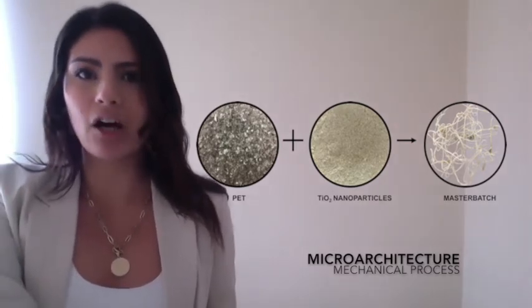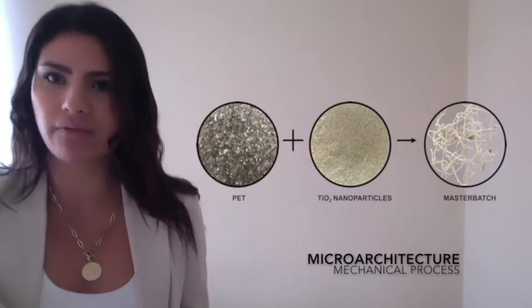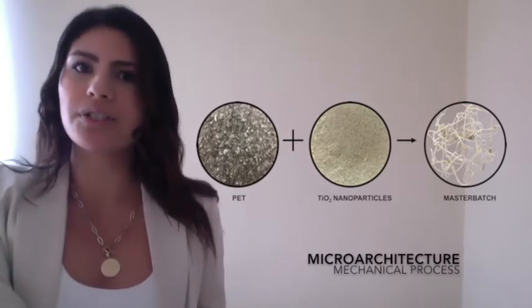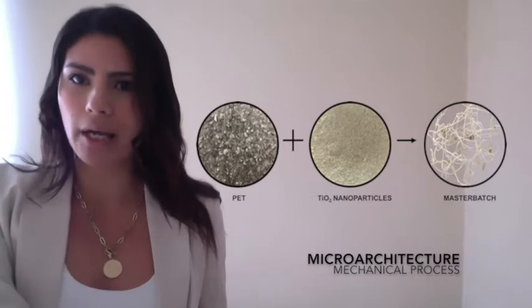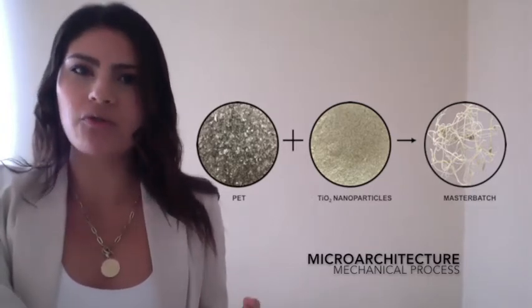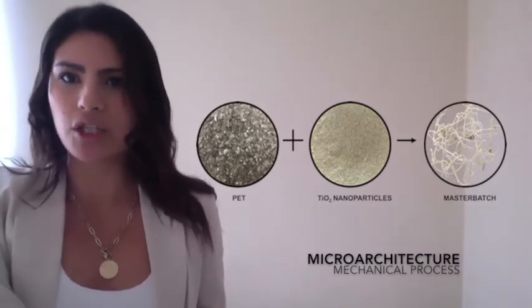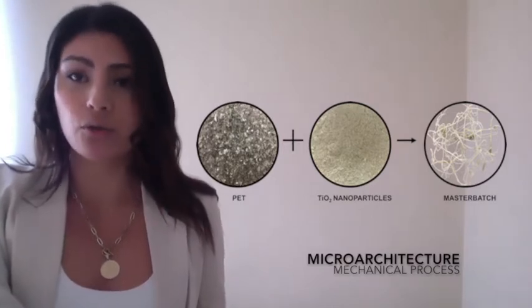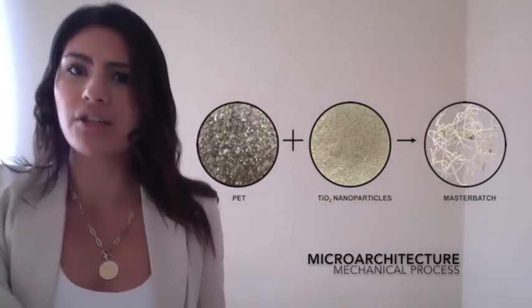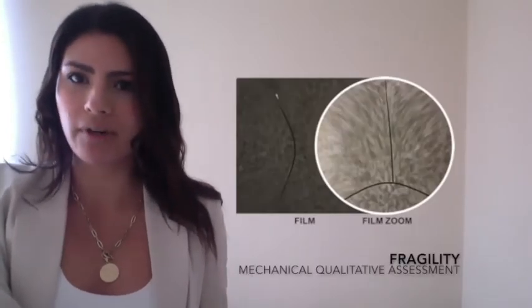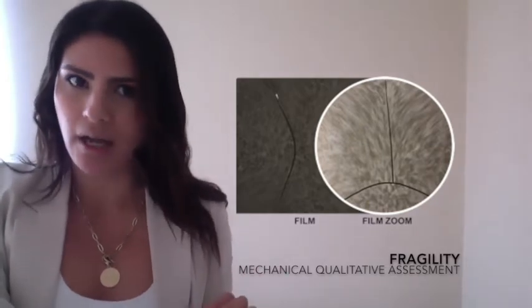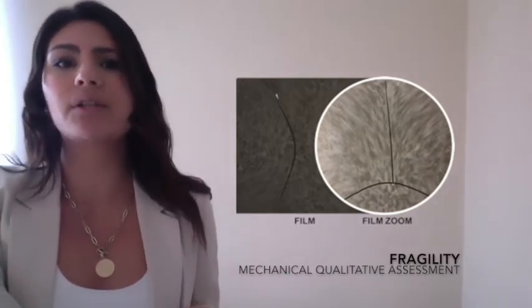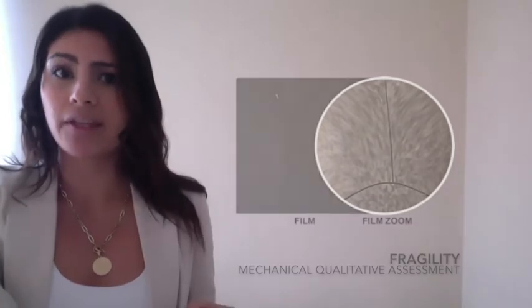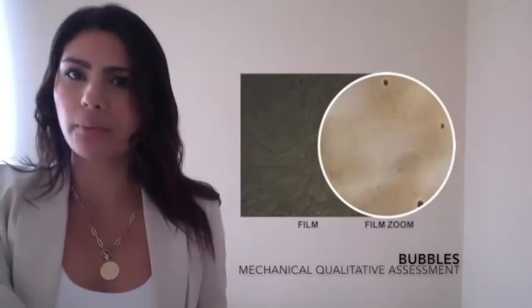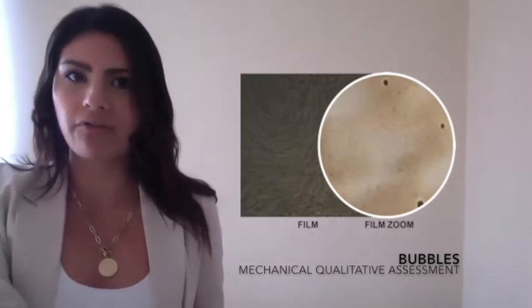Having mechanically combined the two components, the resulting master batch is then pressed according to certain temperature, pressure, cooling time, and pressing time variables to produce films with dimensions in accordance with the Chilean testing standards. Change to the pressing variable results in different behaviors. The amount of moisture absorbed by the master batch must be less than 4%, as greater humidity results in increased fragility.